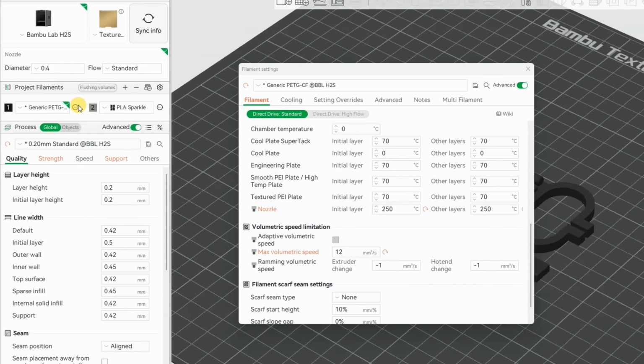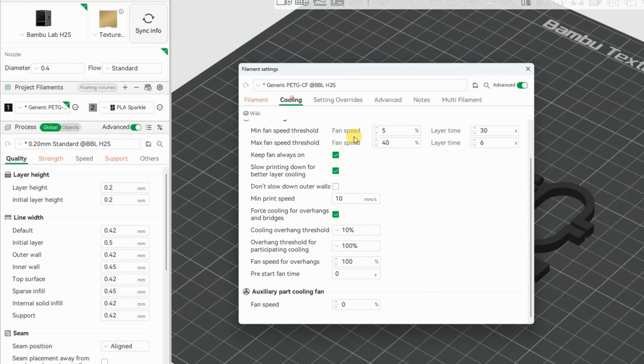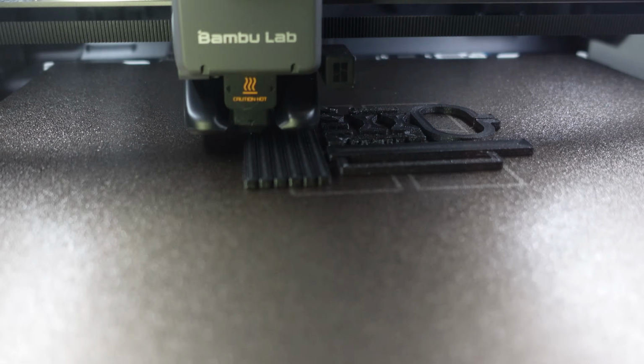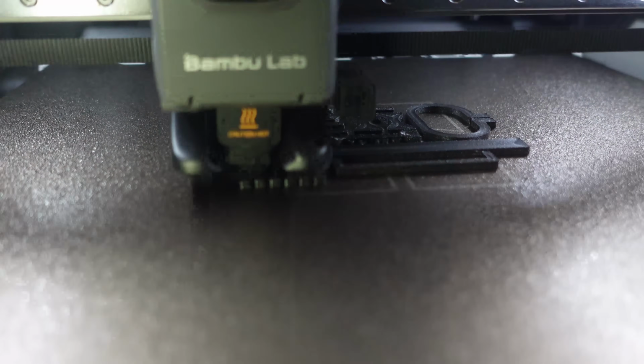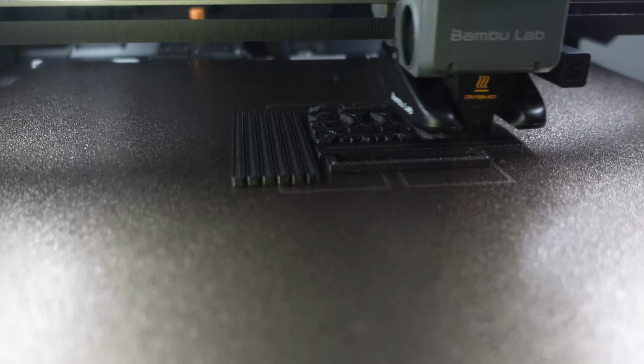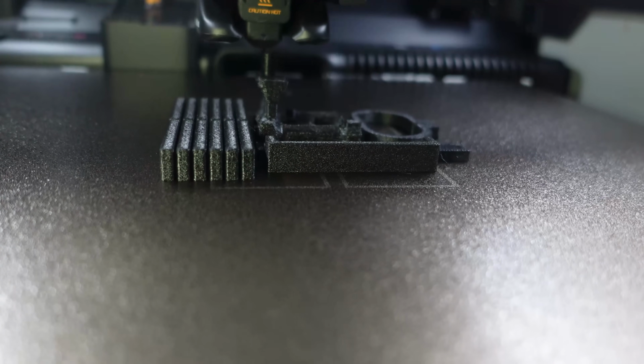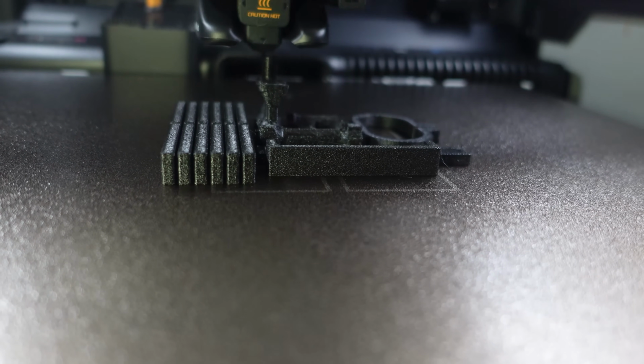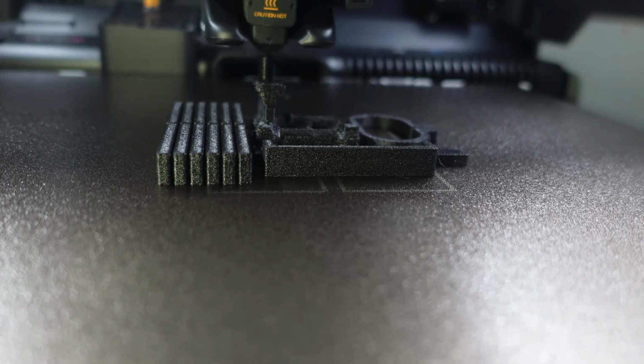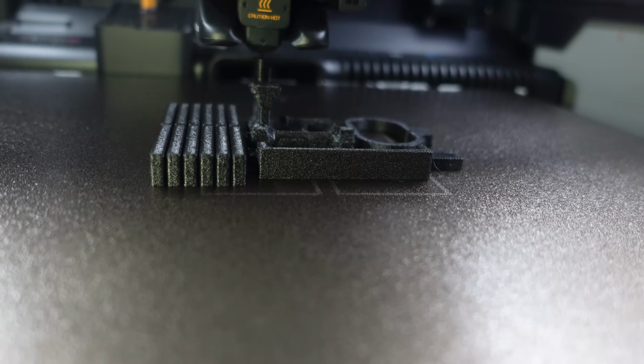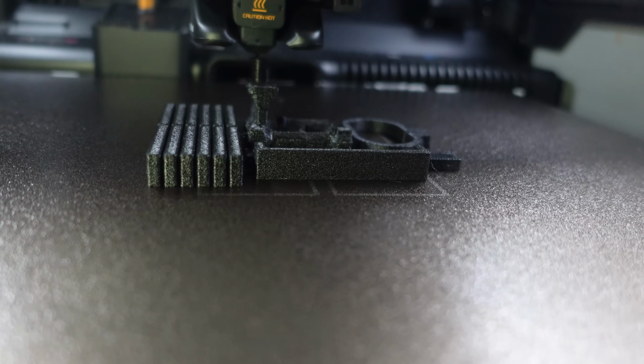Starting from the generic PETG profile, 70 on the bed, 250 on the nozzle, 12 will be the maximal flow, and the part cooling up to 40%. PETG printing is fine too, without any drying, but I will measure the dimensions later. I think we have a perfect example of the wet carbon fiber reinforced PETG, and I will reprint this after the drying, but I will take a closer look first.